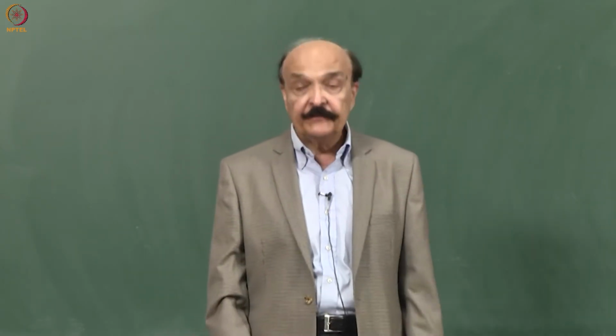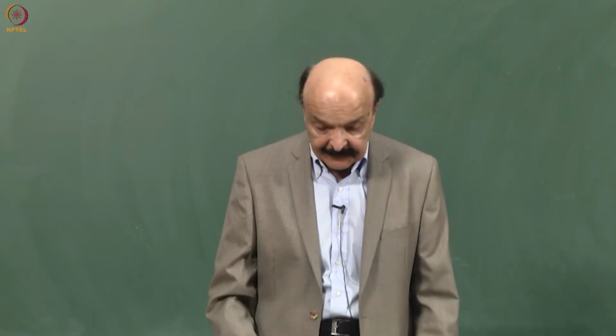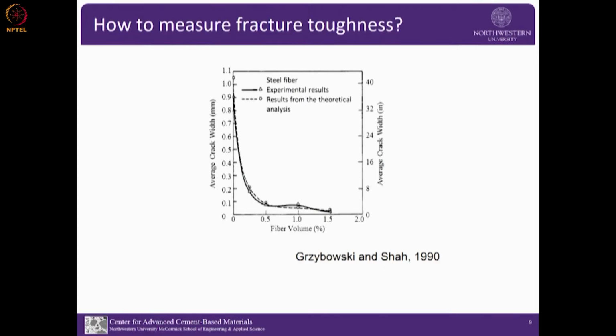And to show how it works, for example, I've shown you some results with steel fiber reinforced concretes. Here is the volume of fiber, and there is average crack width. And you can see as small as 0.5% of fiber volume substantially reduces crack width. And this is why we are using fiber reinforced concrete for crack control.